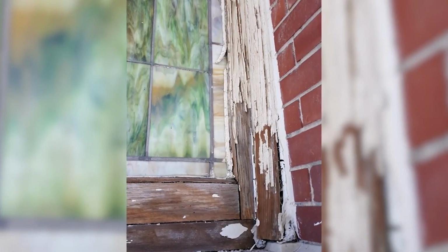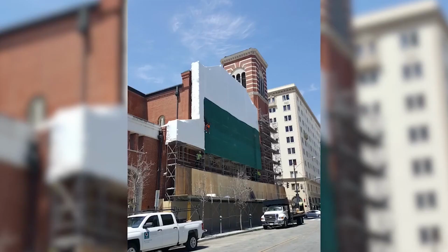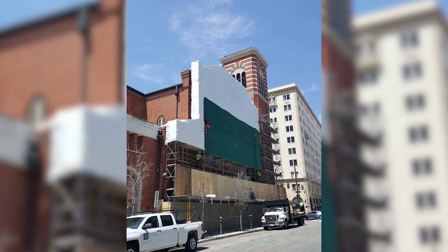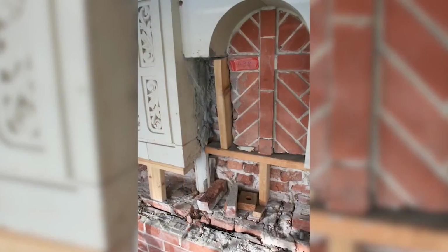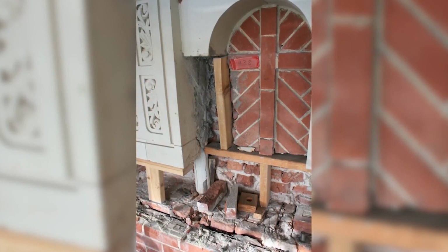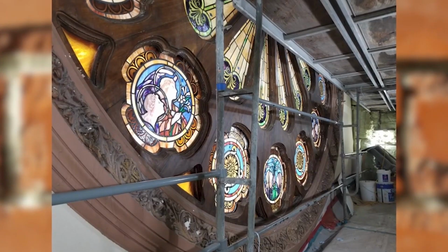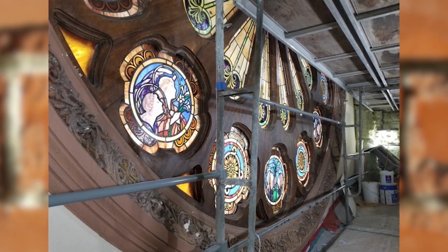We hired a historic preservation expert from the Midwest, and he looked around the building and he looked at the east facade and the terracotta around the rose window, and he said, "You don't have time. You have major problems." Structural damage from the 1933 and 1965 earthquakes was repaired, but no action was taken to address a developing problem with the decorative terracotta that allowed the salty marine climate to penetrate the interior metal structure. By 2017, cracked and spalling rose window tracery posed serious risks of falling.